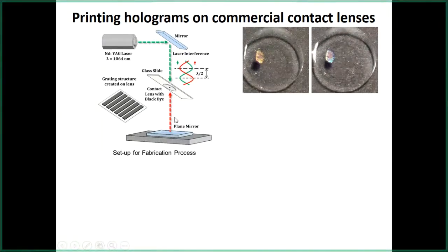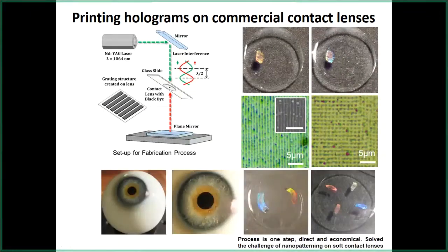When we were optimizing this, as you can see, we used a different laser this time. During optimization, structural damage was also done to the lens, so it would melt very easily. So a lot of optimization of parameters went into this. But after that process, not only did we make 1D nanostructures, we also made 2D nanostructures on the surface of the contact lens. After this, a few companies who had been trying this for a while, but not with the laser approach, contacted us and asked for the parameters and the actual laser that we are using.